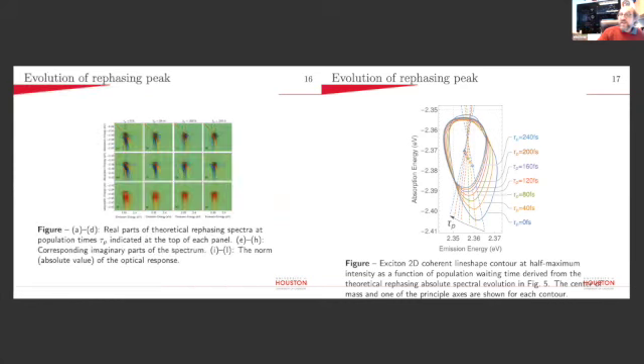The key thing over here on number 17 is the exciton line shape that we calculate from our model, and eventually correlate this to the results in Carlos's experiments. What's interesting is that you see both the evolution of the line shape and its narrowing as you increase the waiting time. So, almost with no parameters, well, there are some adjustable parameters we could try to fit if we wanted to get the exact spectrum, but that wasn't the goal of this. It was really to try to explain the general features of these rephasing spectra that Carlos was showing. And I think we did it.